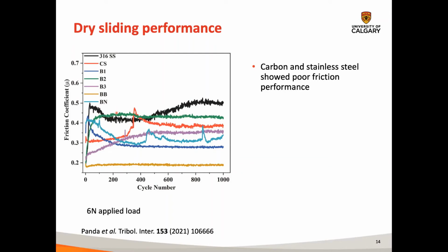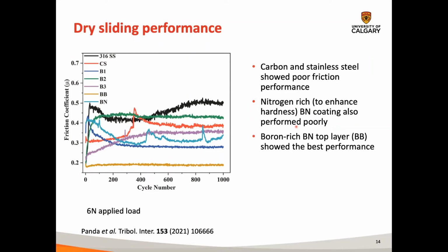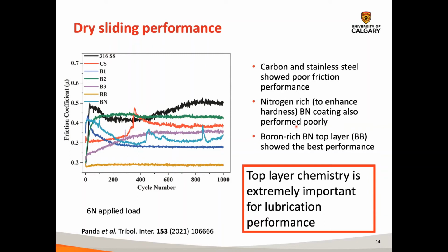So carbon steel and stainless steel showed poor performance. The nitrogen rich, or this sort of hardened coating, didn't perform well at all in these dry sliding experiments. And the boron enhanced top layer performed very, very well in dry sliding experiments. And so what we know from these experiments is that the top layer chemistry is very important. So not all boronized steels are created equally.